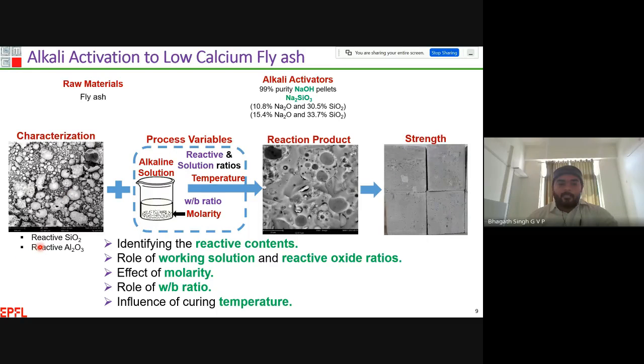Then once I have characterized the fly ash thoroughly, in the second step I have carried out what are the process variables that influence the reaction product. Sorry, that's not about the fly ash characterization, it's the reaction product. Like what is the role of sodium silicate and sodium hydroxide, what is the role of reactive as well as solution ratios, what is the role of temperature and what is the role of water to binder ratio. Here the binder is nothing but the binding material, what we used to call water to cement ratio. And also what is the role of molarity, and how do these process variables influence the reaction product, which means which type of product is formed in the system, how much quantity of product, and also the reaction kinetics.